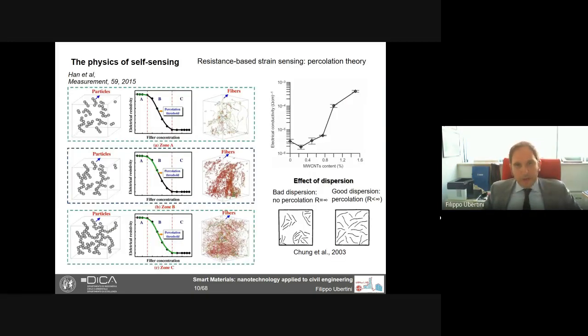Here are a few literature examples of percolation. In the top right, you see a percolating curve in terms of electrical conductivity versus content of multi-wall carbon nanotubes in a smart concrete application. And these results are typical results obtained in our lab, where you see that there is a big jump in conductivity. Note that the y-axis is in log scale, around 1% of nanotubes. What's very important to stress is also that we need a very good dispersion of the nanotubes if we want to achieve such a percolation. And this is very critical, as we will see later on.